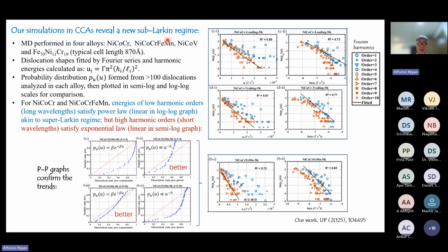So with that background, we began our study some years back on a few CCAs. These are the systems that we looked at: the nickel, chrome, cobalt, and then this 5-element high-entropy system. And again, this one medium entropy, but now with the chromium replaced by vanadium, a stronger pinning site. And there's also another alloy system. So we ran the MD simulations as I have described. We generate a lot of dislocations, pass them through the slip plane, analyze their shapes, fit their shapes using Fourier series, and back out the harmonic energies as calculated by this term.